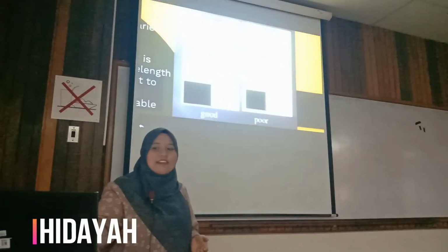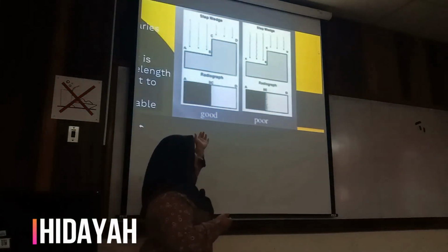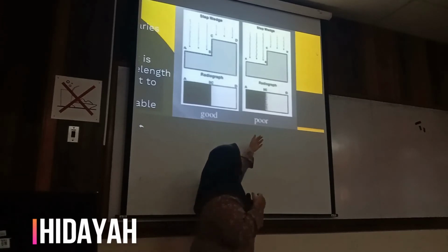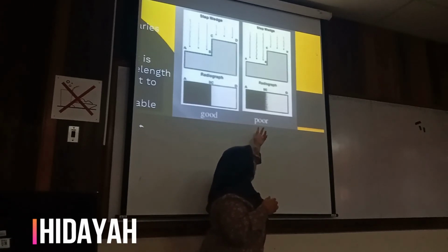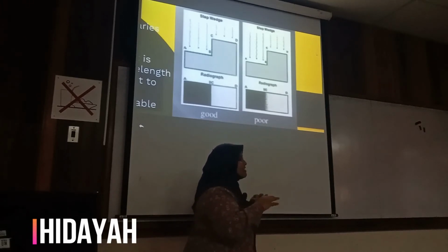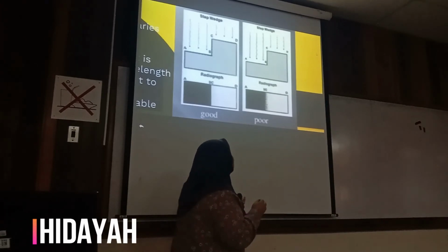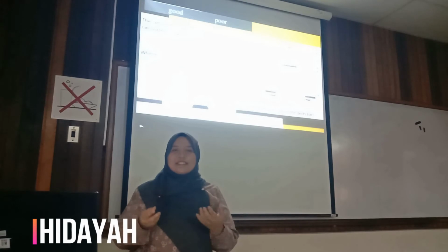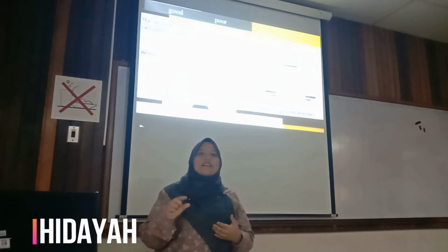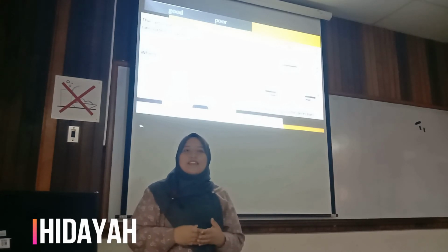So we can see here, this one is a good definition of image produced, and this one is a poor definition of image produced. And we can see this is the amount, like I said before, of unsharpness formed due to high energy use. In industrial radiography, low definition can happen, but it is limited to a certain amount. So the unsharpness can happen, but it is limited to 1/100 of the thickness of the subject being observed,